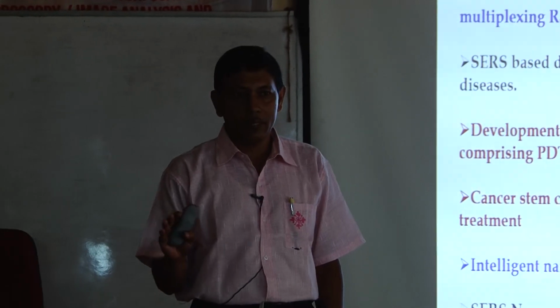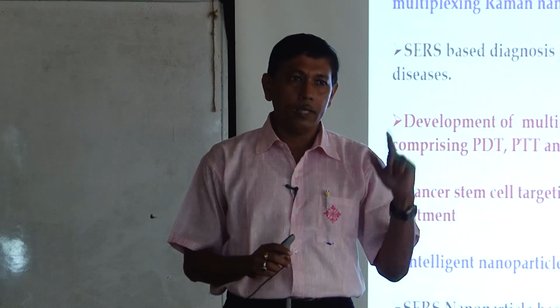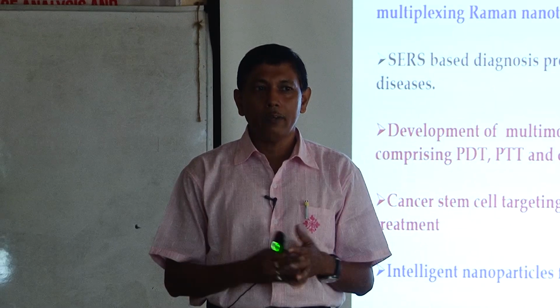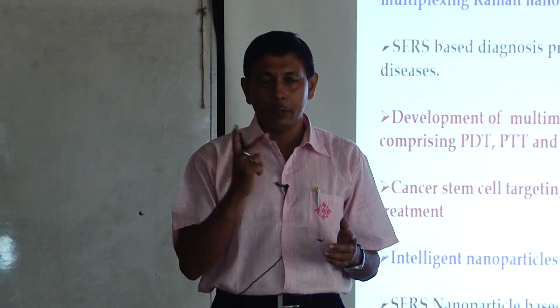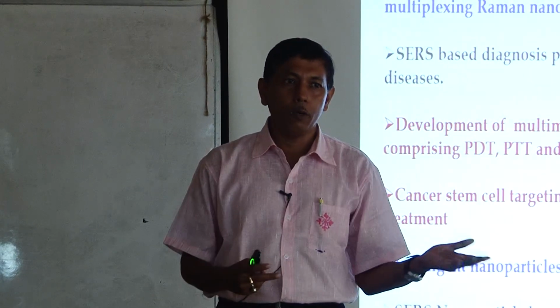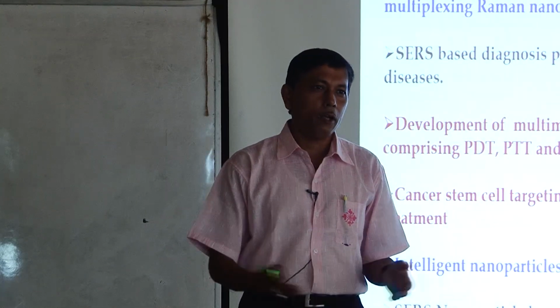What is the Raman activity of copper nanoparticles? Copper has been tested in a few cases, but it is not a good Raman or SERS substrate. It can be used as a substrate, like gold and silver, but it was found that in the two mechanisms, electromagnetic enhancement and chemical enhancement, it is not so impressive as gold or silver. So, it may be used, but it may not flourish.